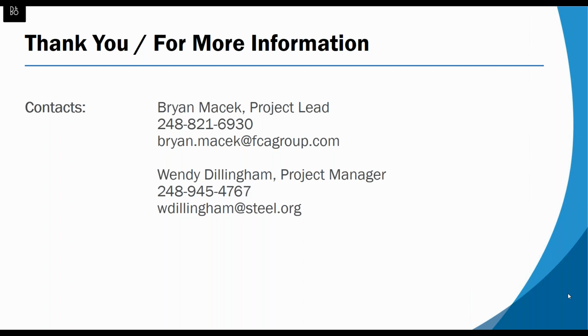Wendy, this is John. I don't think the main audience can ask directly, but Brian, I think I can clarify this. At some point during the presentation, you said that if you increase the load because it was an adhesive joint. I remember that, yes. I think the question is, had you run the two joints at the same load, would they have been equivalent? Well, certainly when we ran the joint with just the sealer and not the adhesive, they performed fairly well in cyclic, so I don't think that would be a problem. It was just the particularly high loads we saw with adhesives where we saw a significant divergence in the cyclic load performance. And that's probably due to the material itself now rather than the joint, Brian, probably, right?